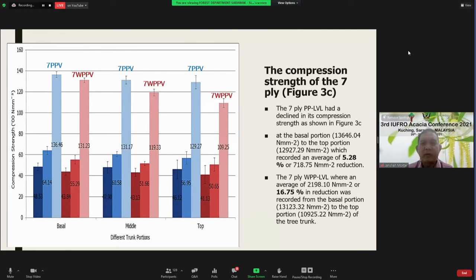And the compression strength of the seven-ply, as you can see in figure 3C, the 7-ply PPLVL had a decline in its compression strength from the basal portion to the top portion, which recorded an average 5.28% reduction. Meanwhile, for the seven-ply without prepressed veneer, an average reduction of 16.75% was recorded from the basal portion to the top portion of the tree trunk.